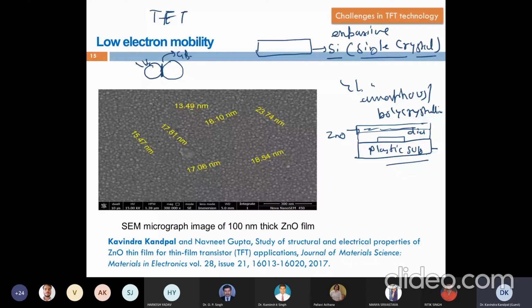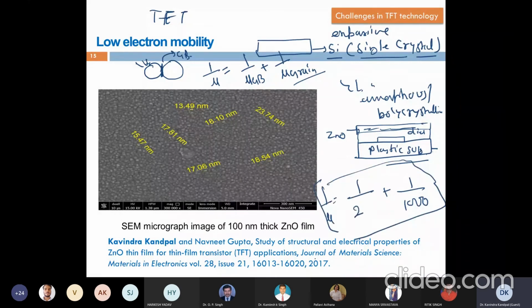You might know the mobility in a semiconductor is a harmonic mean: harmonic mean of mu of grain boundary plus mu of grain. As I said, the mobility within the grain will be as good as silicon, because grains means almost single crystal silicon. Let's say mu grain is 1000 centimeter square per volt second, which is very good mobility, but within the grain boundary, the mobility is only 2. So what will be its equivalent? 2 or 1000? When you are taking the harmonic mean of two quantities, one very high, one very low, which will dominate? 2 or 1000?